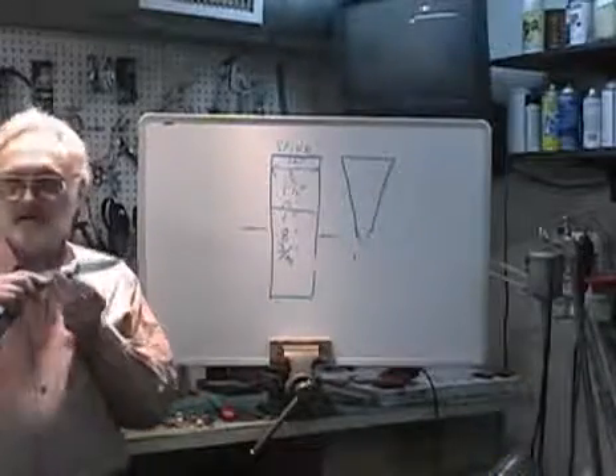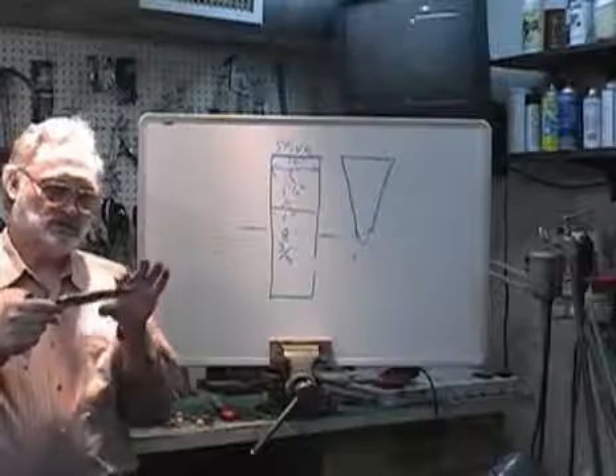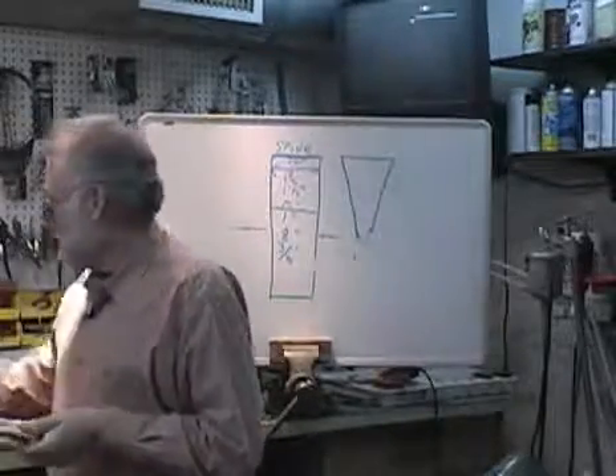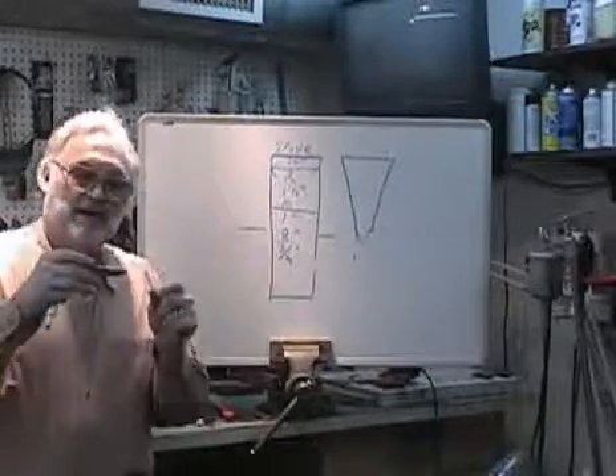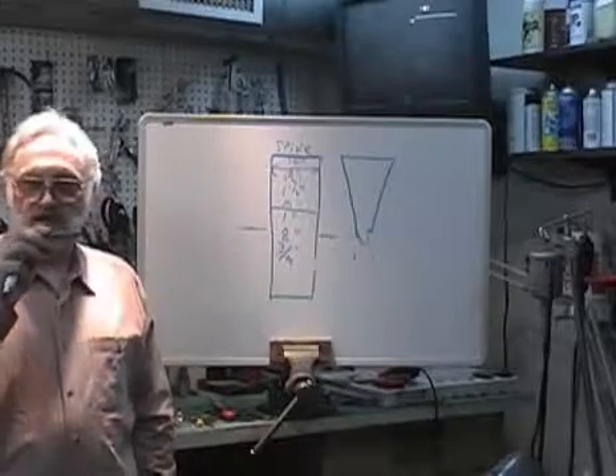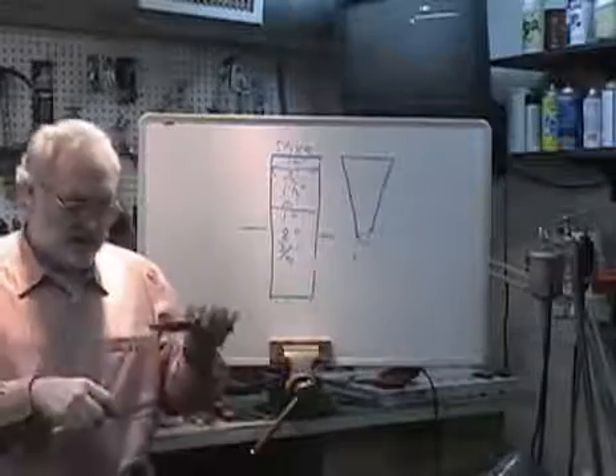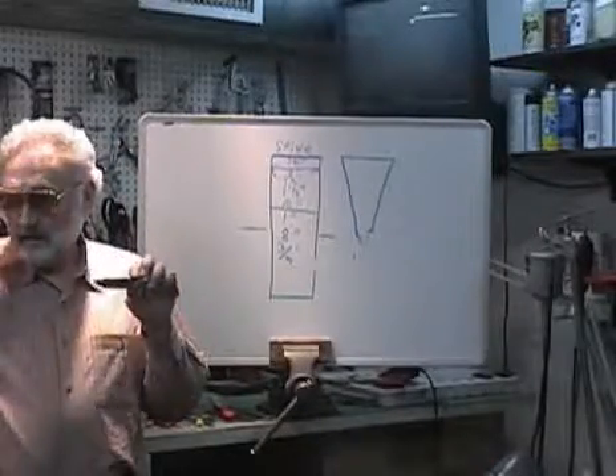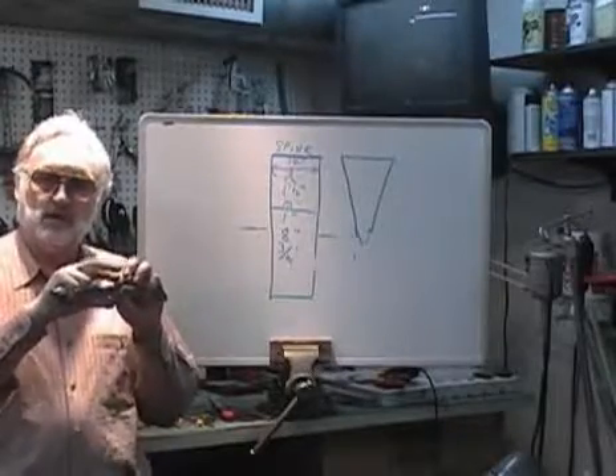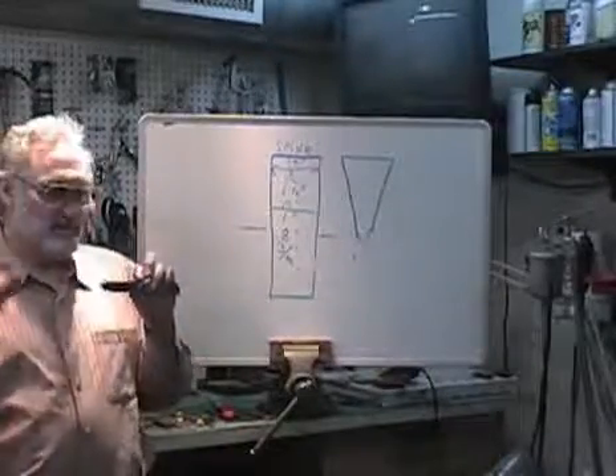That's the reason when we ground this blade, we ground it with a 10-inch wheel, because this is approximately 1 inch tall, okay? The smaller folder blades were about 3/4 of an inch, and that's why I elected to use the 8-inch wheel on those. Now, had my hunting knife been about 1.5 inches, although I don't have a 12-inch wheel, I would have needed to step up to a 12-inch or step all the way up to my 14-inch wheel, which I could do.